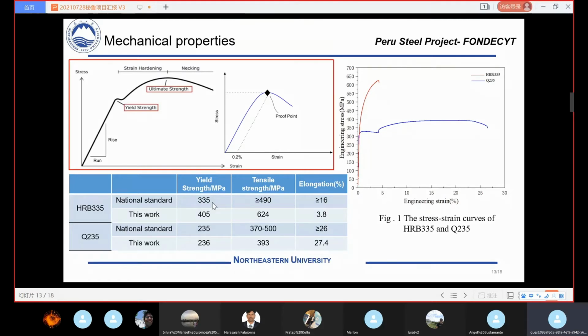We can find that the yield strength of the HRB 335 is 405 megapascal, and the tensile strength is 624 megapascal, and the elongation. However, the elongation is small, just 3.8%. However, the yield strength of the Q235 is 236 megapascal, and the tensile strength is 393 megapascal, and the elongation.